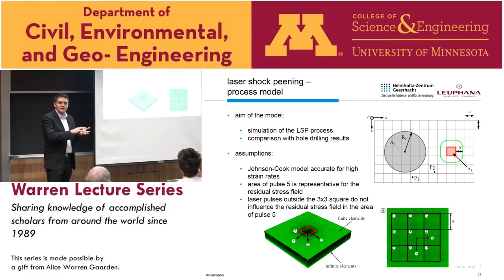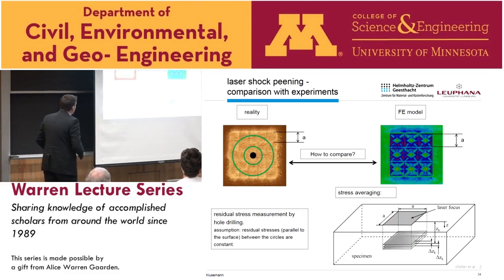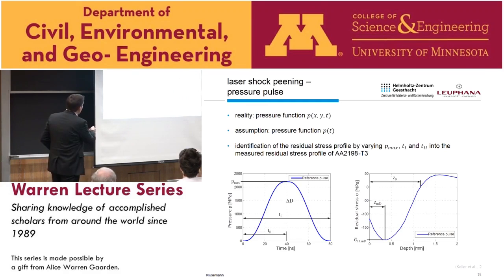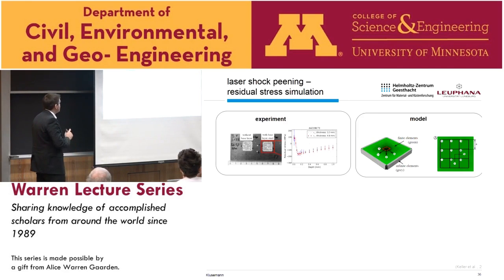I will skip over this. So we have, of course, taken a Johnson-Cook model in our simulation, and we had to develop a method how to actually calculate now our stresses in simulation to be comparable to hole drilling. So we had to take some average over a surface. We developed this here, and of course, one important question here was how to import the pressure field inside of our simulation. So we used this pressure pulse. And we could identify this on experimental data to have the accurate response of that.